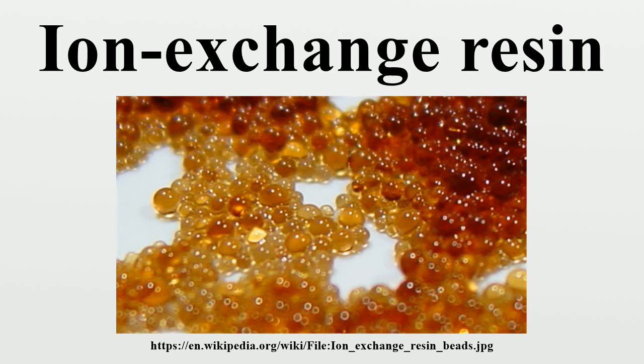Ion exchange beads are also an essential component in in-situ leach uranium mining. In-situ recovery involves the extraction of uranium-bearing water through boreholes. The extracted uranium solution is filtered through resin beads, which attract uranium via an ion exchange process. Uranium-loaded resins are then transported to a processing plant where U3O8 is separated from the resin beads and yellowcake is produced. The resin beads can then be returned to the ion exchange facility where they are reused.